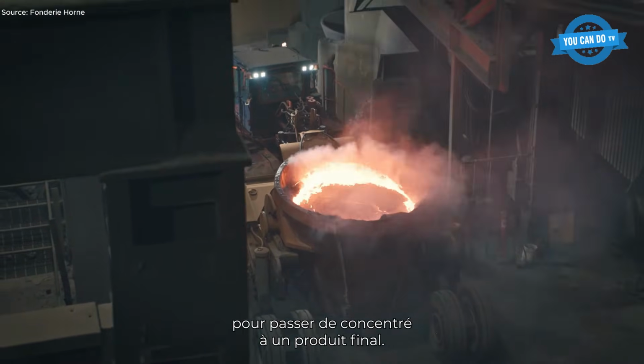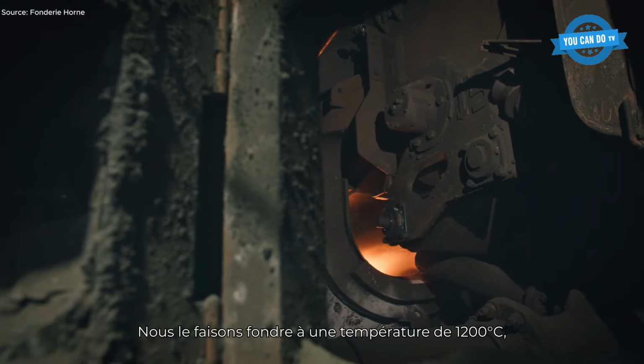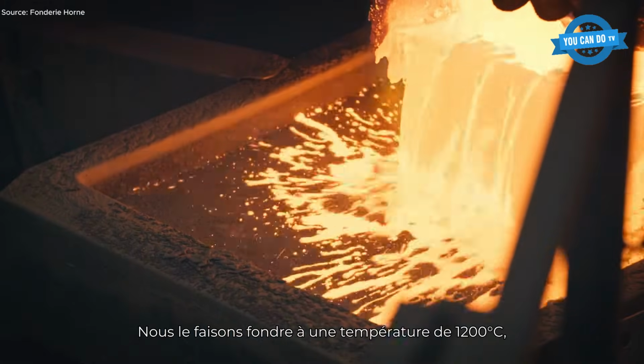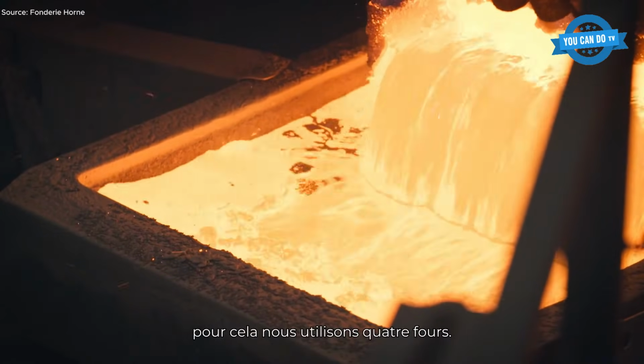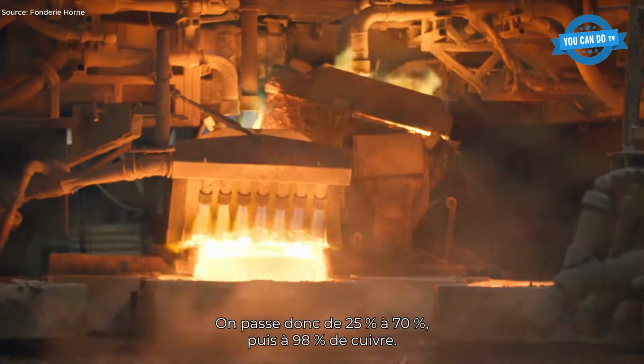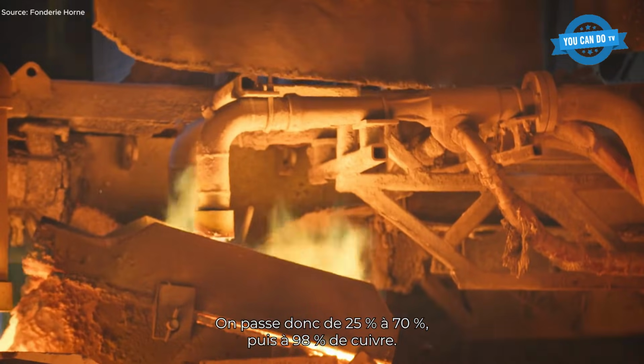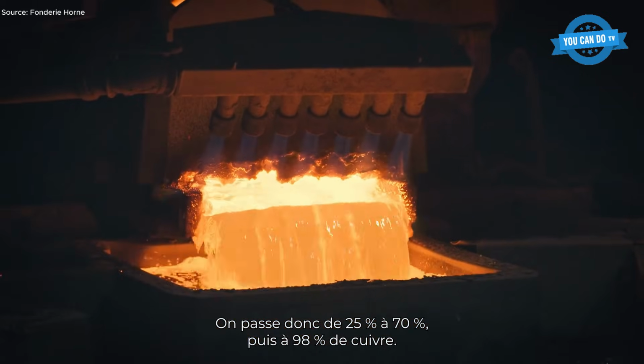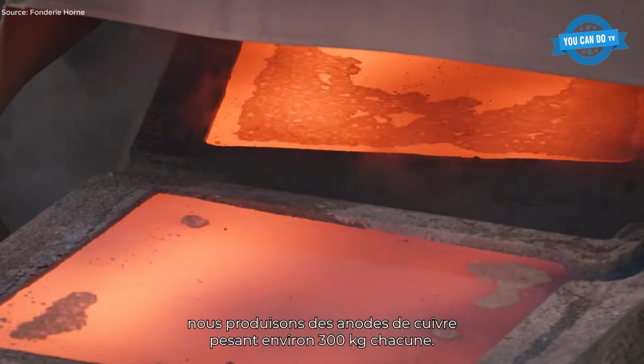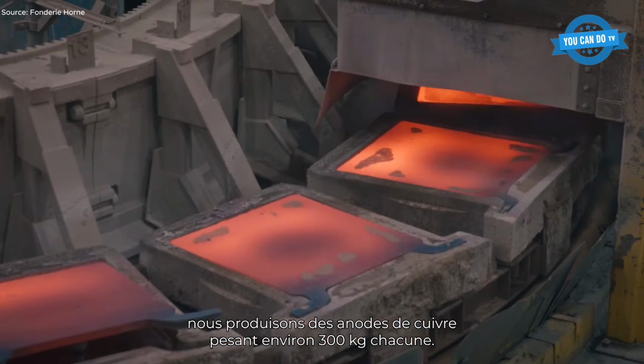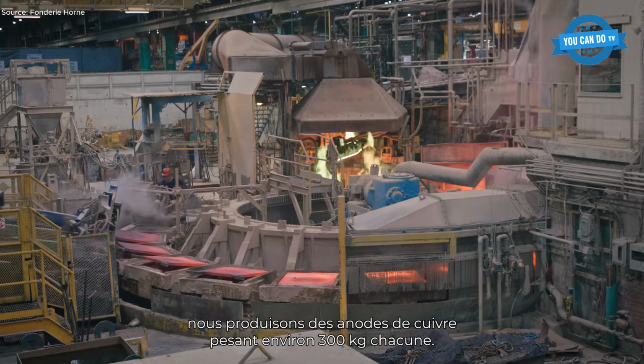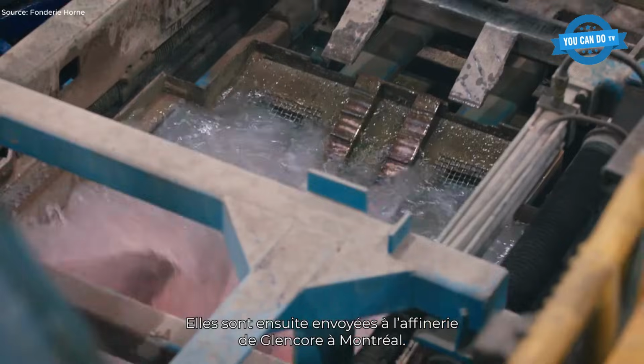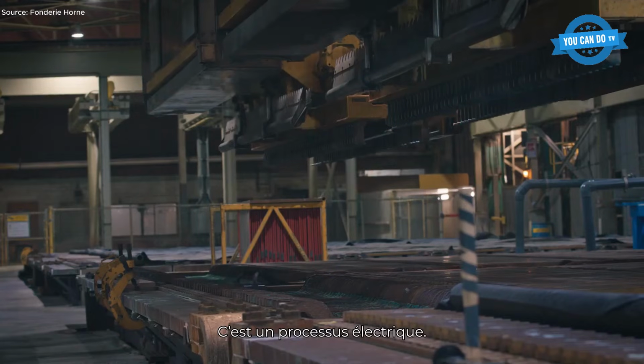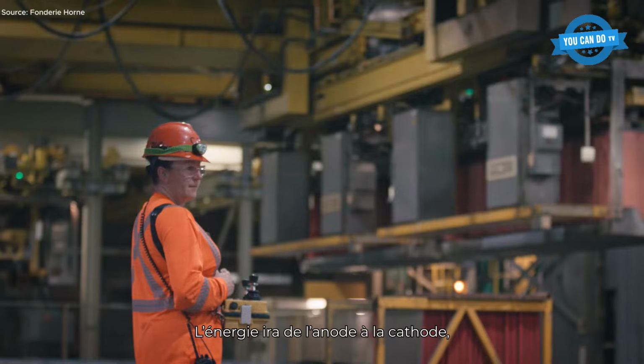Subsequent smelting occurs in high-capacity furnaces at temperatures up to 1,200 degrees Celsius. Copper recovery, for example, is achieved through staged melting in 4 sequential furnaces, with each stage refining metal concentration from 25% to 98%. Resulting copper anodes, each approximately 300 kilograms, are sent to electrochemical refineries where they achieve 99.99% purity.